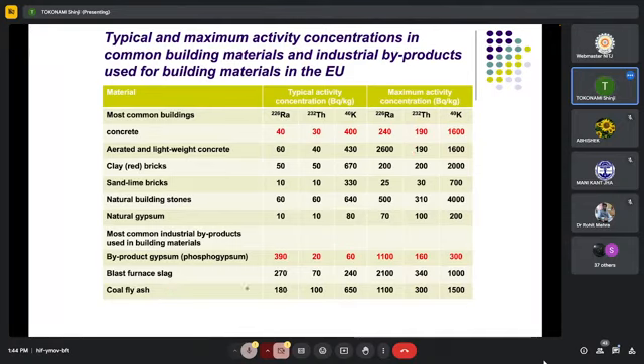Coal fly ash, as a typical value, 180 for radium, 100 for thorium, and 650 for potassium. 1100 for radium, 300 for thorium, 1500 for potassium-40 as a maximum activity concentration in becquerel per kilogram.